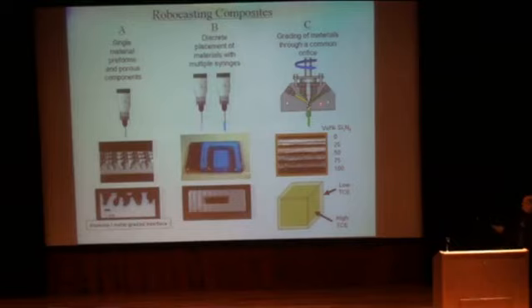Here's an example where we went from 100% silicon nitride on this layer and then functionally graded this material to 100% tungsten on the top layer. Silicon nitride and tungsten you could never co-fire just side by side, but by doing a functional grading, you can co-fire these. Now you go from 100% ceramic to 100% metal in one operation.